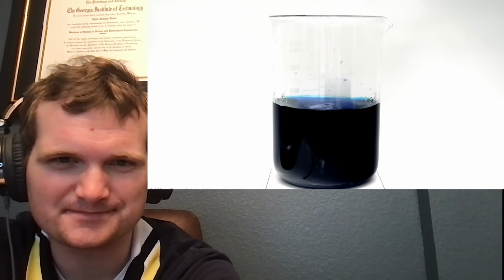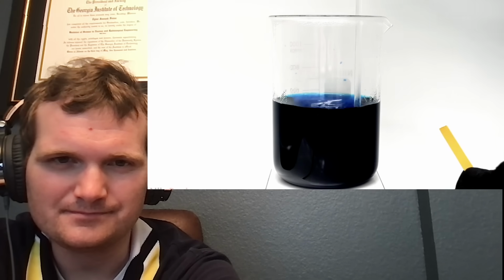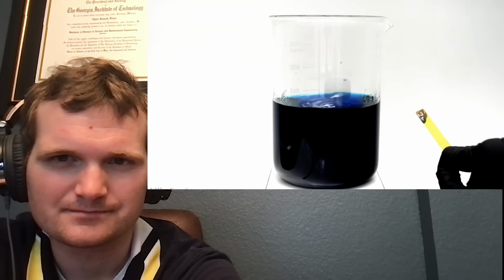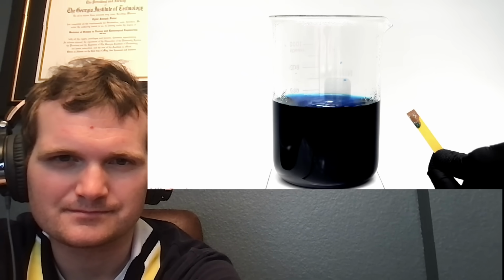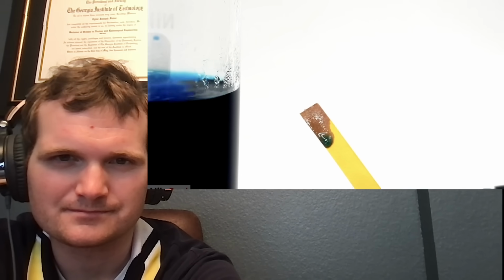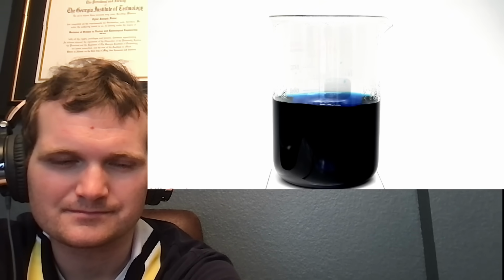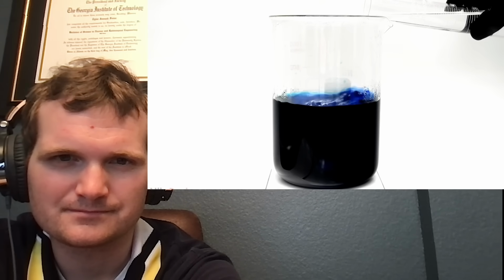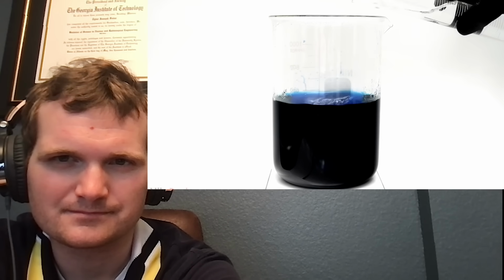And now it's dark. After adding a decent amount, I let it stir for a few minutes, and I checked the pH again. It now looked like it was around 5, which was better, but I still had a bit to go. So from here, I just kept adding small amounts of ammonia and checking the pH.